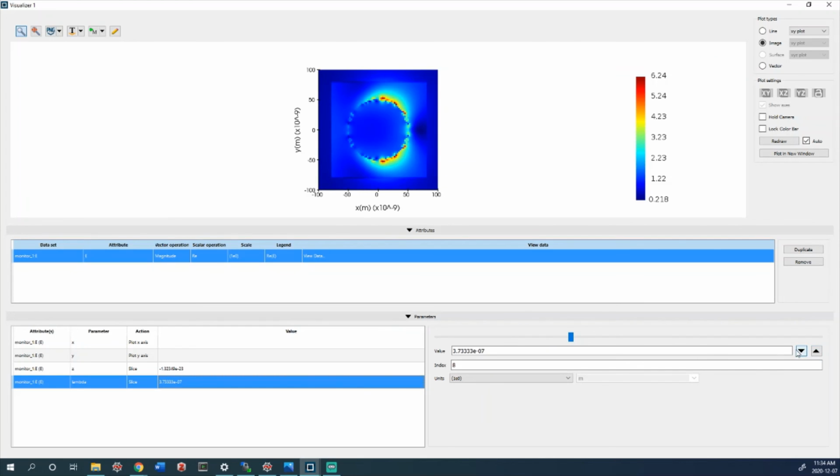Oh, over here you can see that the electric field is, so this is at 400 nanometers. Yeah, so around 400 nanometers, 430 nanometers, we get that the electric field is almost 8 times larger than the electric field that we actually sent in. So that's what plasmonic particles do. They enhance the electric field that we sent in. So yeah, that's the time domain electric field.